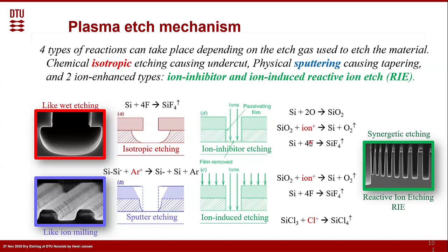And then the fluor radicals, who are just waiting here all the time in huge quantities, because we remember maybe from the plasma fundamentals that the radicals are normally like 100 times more available, let's say, than the ions. So the radicals are just waiting to attack again the silicon, which has just been freed at the bottom by the impact. And you get again silicon tetrafluoride. Due to this process, it's quite fast. It can be very fast because this one is still the reaction controller.